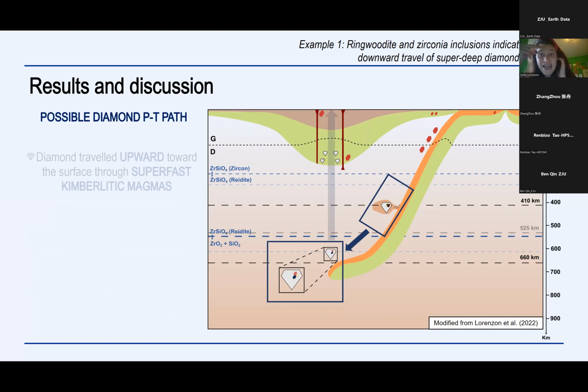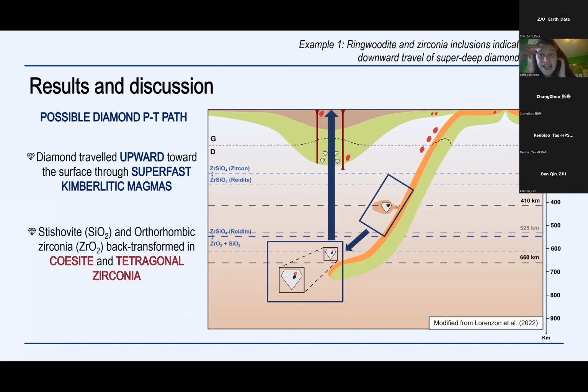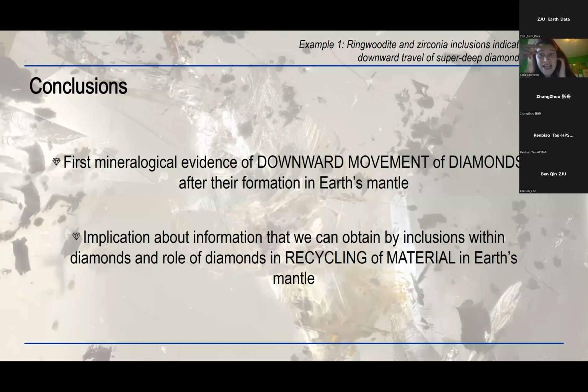Finally, this diamond traveled upward, probably transported by superfast kimberlitic magmas, and during the travel, the original orthorhombic zirconia and stishovite back transform into tetragonal zirconia and coesite. So, in conclusion, what did we obtain from this study?